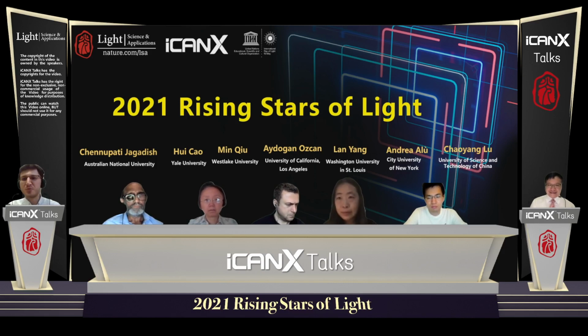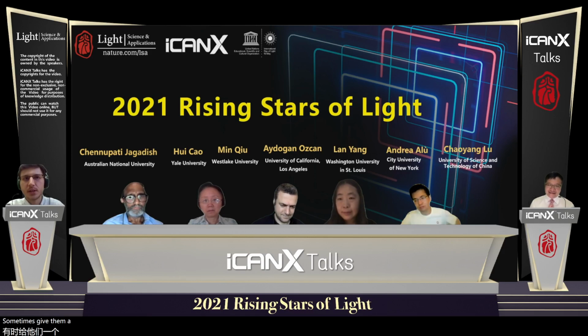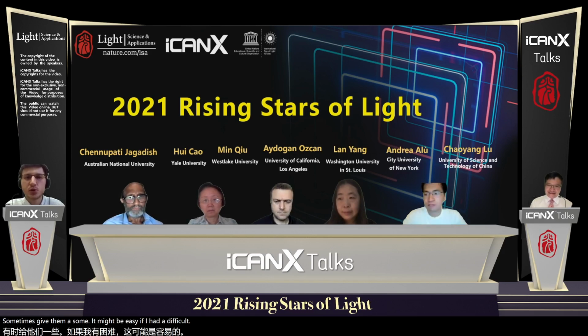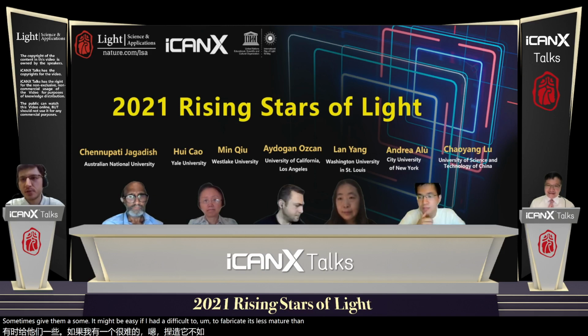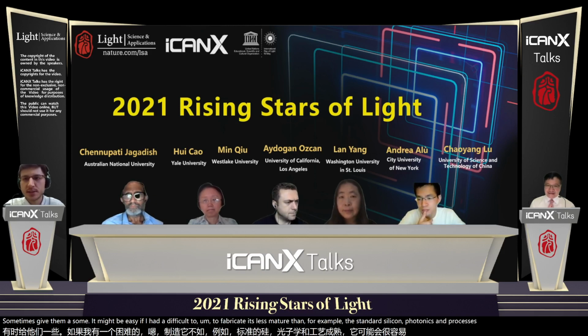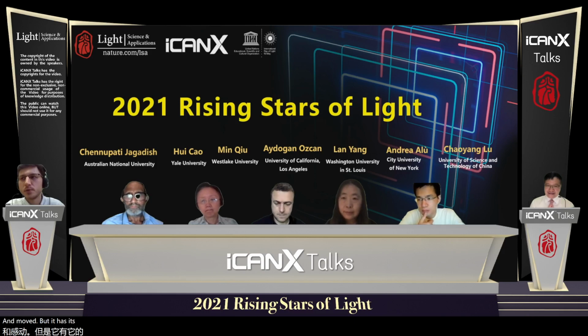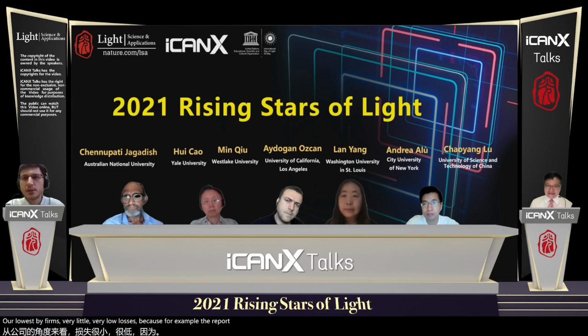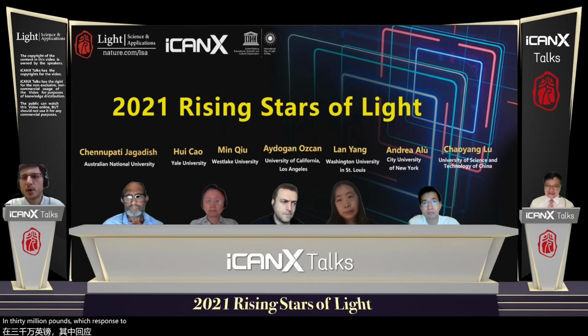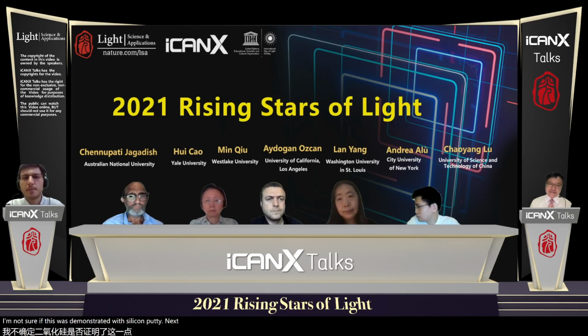Well, I was mostly working with silicon nitride, so I would obviously advocate for silicon nitride performance. It might be difficult to fabricate, and it's less mature than, for example, the standard silicon photonics processes. But it has its own advantages: very low-loss platforms. For example, they're reporting, I think, 30 million Q, which corresponds to less than 1 dB per meter, which I'm not sure was demonstrated with silicon photonics. Then it has a higher nonlinearity than silicon, which also helps.